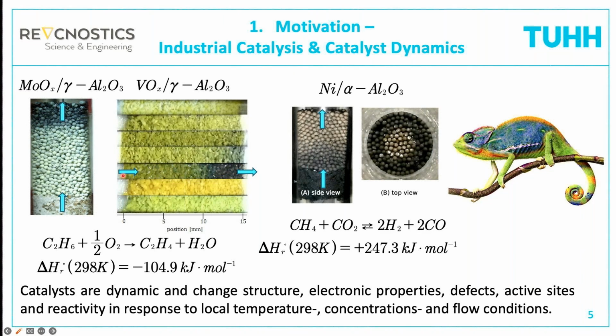You can do the same reaction on a vanadium catalyst, and you see yellow. So vanadium +5, and then as the oxygen gets consumed, it turns greenish, bluish, so oxidation states +4 and +3. And this shows how dynamic a catalyst is. On the right side, you see a nickel catalyst supported on alpha alumina for dry reforming of methane, and you see that the catalyst is coking up. We have coke formation in flow direction and also in radial direction. And all of this is not included in any kinetic model. We treat this on a very simplified level.